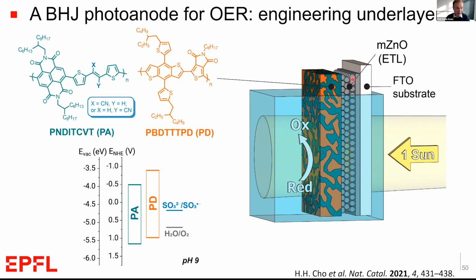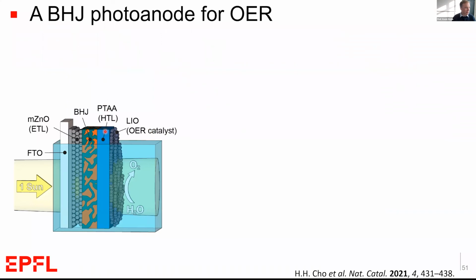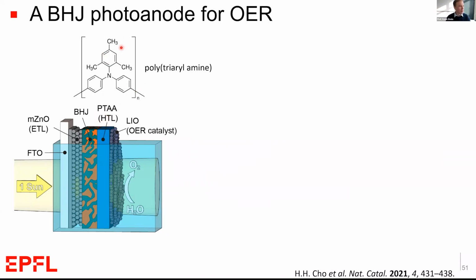But when Professor Cho decided to put in the mesoporous zinc oxide, a nanoparticle zinc oxide substrate with a very, very high surface area, this gave more surface area for the bulk heterojunction to adhere to. And that drastically improved the stability. First, we observed that under the sacrificial sulfite oxidation conditions. But that's also true when we built the entire system and put the PTAA hole transporting layer on top, which is the second invention that Cho made to improve the performance.